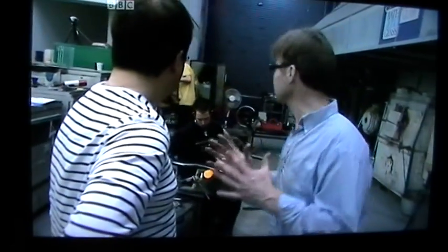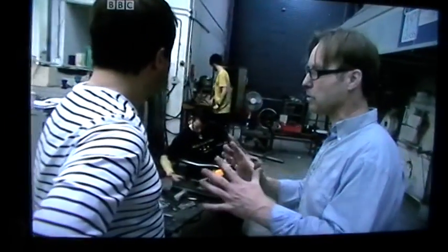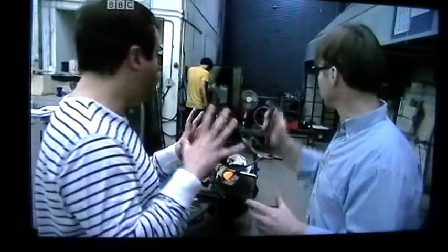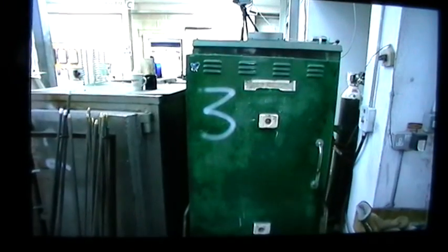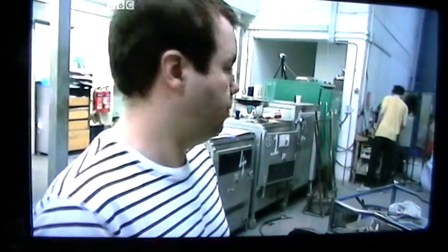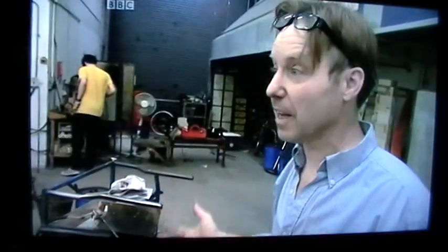And I've just handed that over to Connor, because that cannot stay out. If we leave that out on the side, it would crack as it cools down. So what happens now? We have to soak it at 420 degrees centigrade in a kiln. What would be called a kiln, but we call them lehrs. It's just in the glass world.